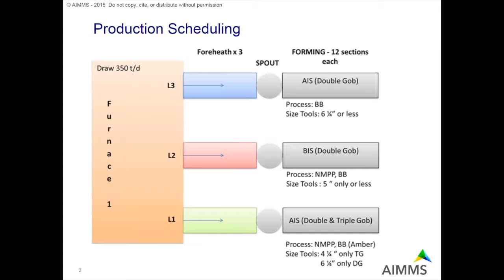The difficulty in this scheduling process is that all 12 sections times the three outlets — the total draw, the total production — should be as close as possible to 350 tons per day. If you go bigger the quality of the glass deteriorates; if you go below, the same happens and you reduce utilization of a really expensive asset. So you have a very difficult interaction and interdependency between different production batches while still meeting demand. Having three foreheaths makes this even more difficult.